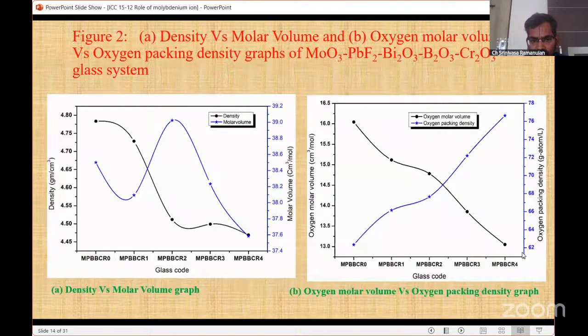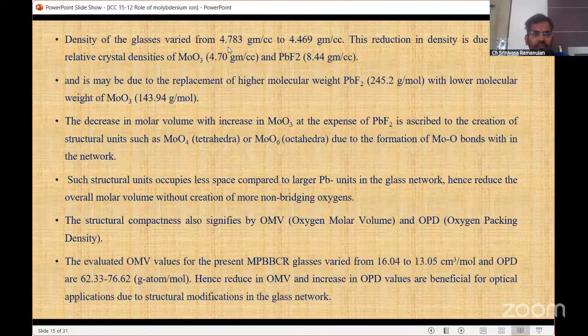And this is a graph between oxygen molar volume and the oxygen packing density. Density is decreasing from 4.7 to 4.6, 4.4. The reason may be that the sample initially had a larger concentration of lead fluoride, which is replaced by the lower density molybdenum. That's why the density may be decreasing. That's one point we can say. And the decrease in molar volume may be due to PbF2 being replaced by MoO3, so there may be a change in the structure.